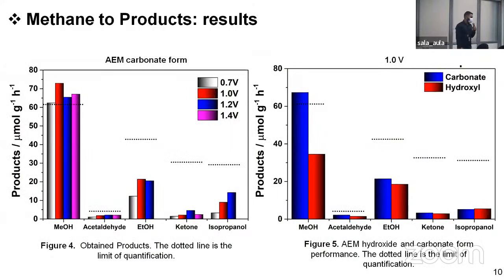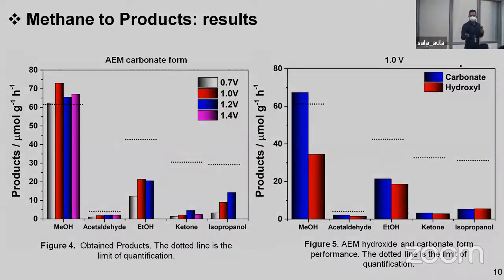In the results, after identification and quantification, we obtained several compounds: alcohols, aldehydes, ketones. Methanol is the product in greater quantity than the other compounds. 1 volt is the best potential for methanol formation. And finally, it's possible to observe a comparison between the ion exchange membrane in carbonate form and hydroxyl form, and we can observe that the concentration of products is lower when using the hydroxyl form. Thanks.